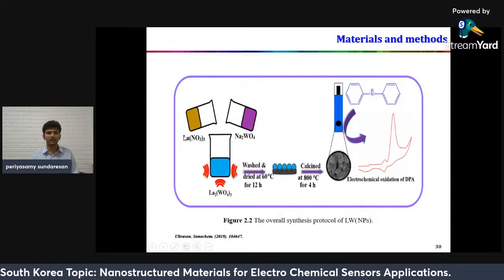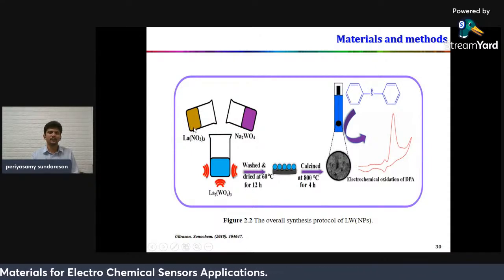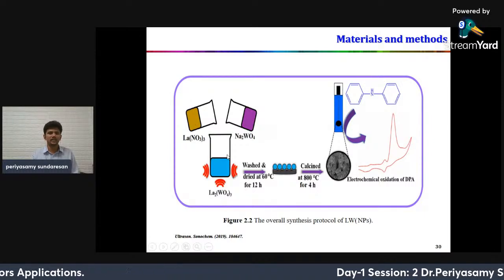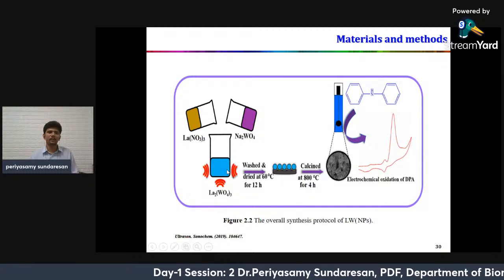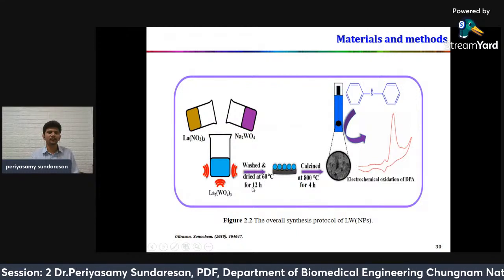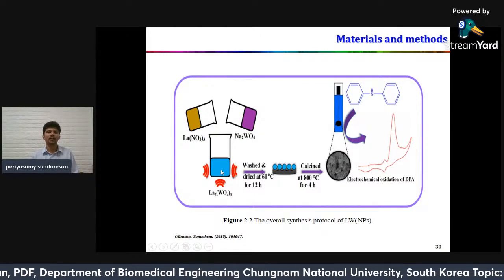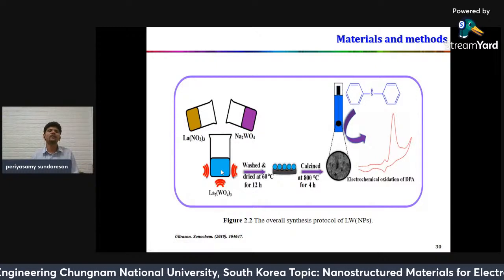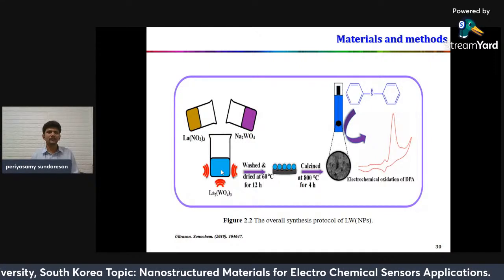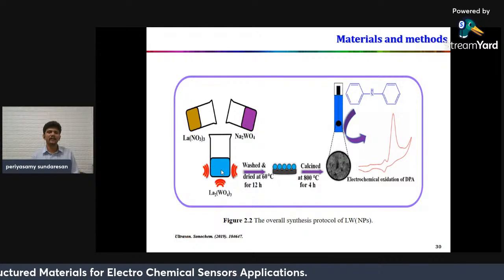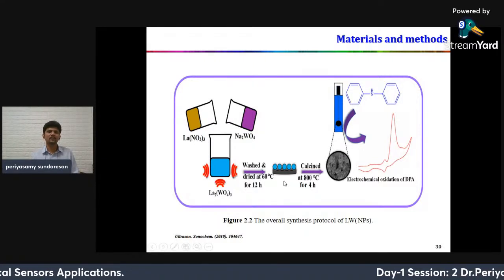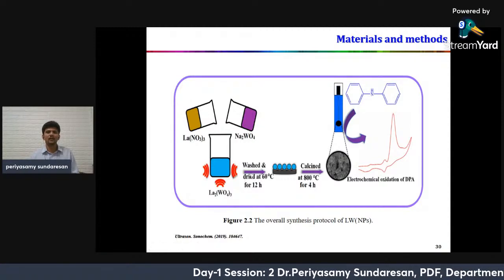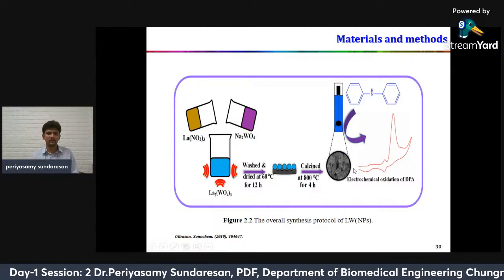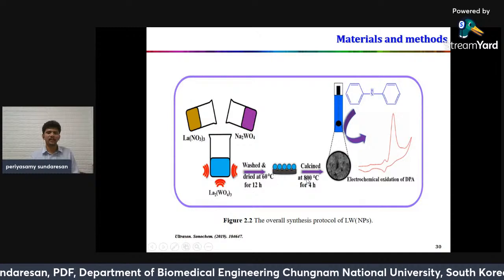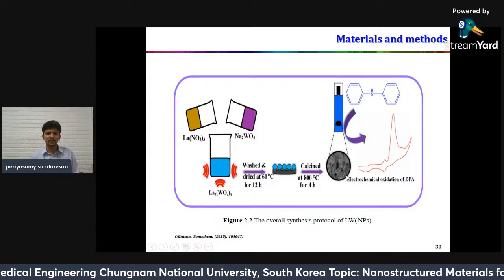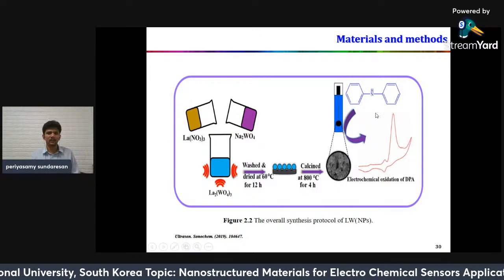Initially I took lanthanum nitrate and sodium tungstate. Both are mixed with water, and after the addition, the whole mixture was placed into an ultrasonication bath at 60 degrees centigrade for 12 hours. In the presence of ultrasonication, it creates bubbles, and the sound waves induced affect the material morphologies and can enhance the structural properties. After the sonication process, I checked different calcination temperatures, like 800 degrees centigrade for 4 hours. Then I get the lanthanum tungstate nanomaterial, which will be applied for electrochemical sensing.